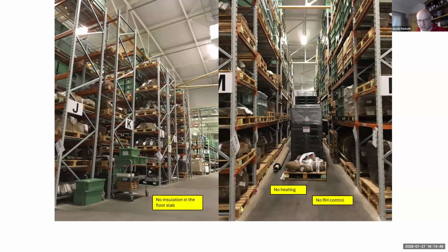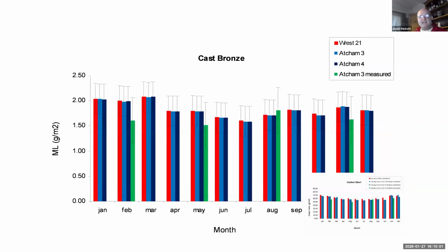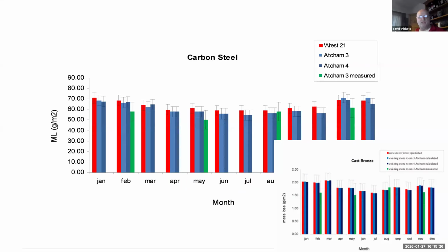Before we built the store, we wanted to compare the conditions where the material was already being stored, as it was brought from several stores around the country, to what we predicted was going to be happening here. These are predictions for cast bronze. Red is what we thought the new store was going to perform like. The 2 blue lines are 2 of the rooms where the material was, and the green line is actually a measurement of copper corrosion rate in there, not the damage function. You can see it's fairly similar. Similarly for carbon steel. So we were as confident as we could be, without building the thing, that it was going to be okay.